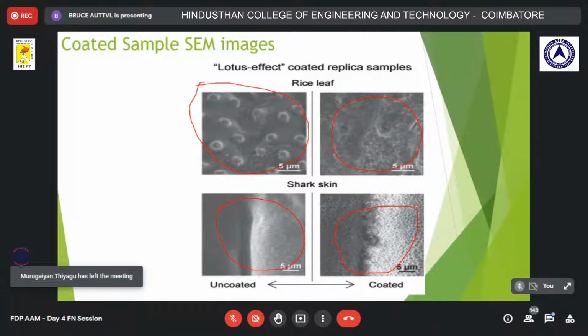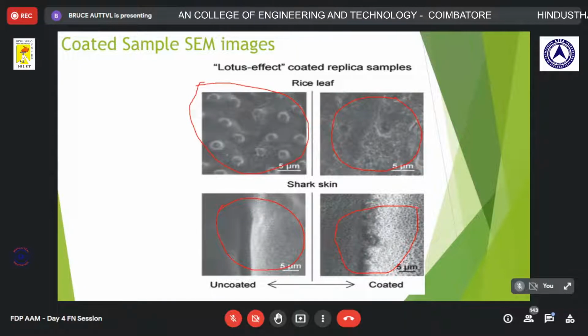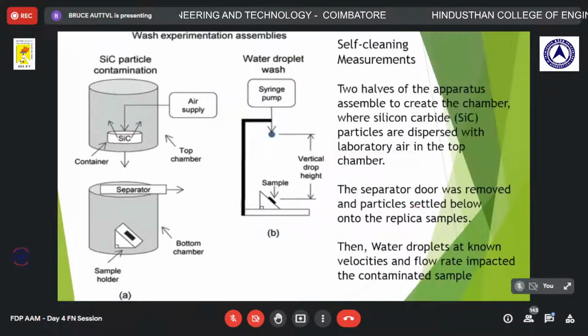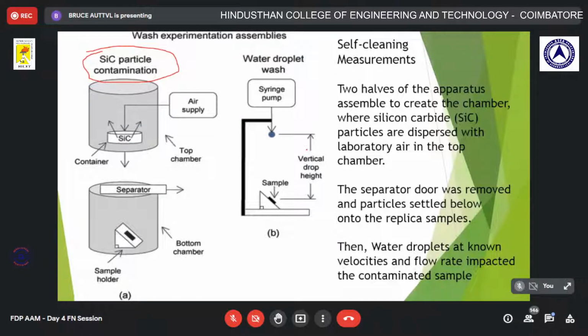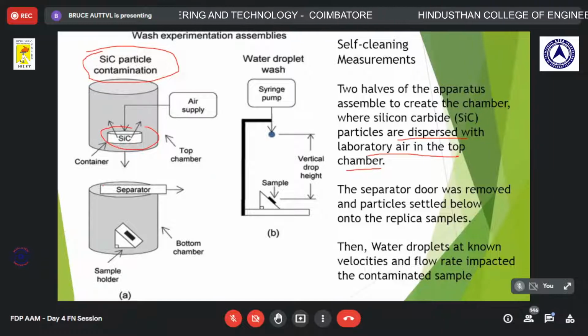And nowadays, extensive facilities are available even within our state to prepare all these kinds of specimens. Okay, and the self-cleaning characteristics can be studied through these wash experimentation assemblies. Here you can observe a silicon carbide particle contamination strategy. Here, two halves of the apparatus are assembled to create the chamber where silicon carbide particles are dispersed with laboratory air in the top chamber. And once the separator door is opened, the particles are allowed to settle on the replica samples. Okay, here it will be settled.